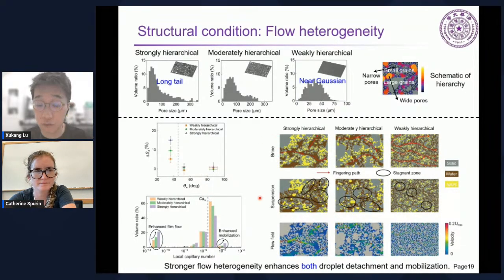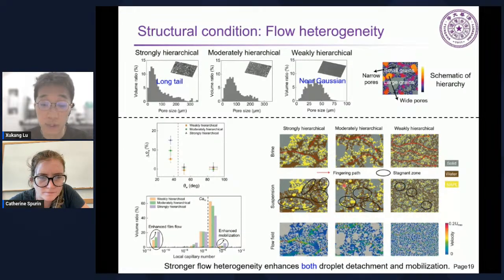And we try to analyze it from the qualitative comparison between the phase distribution and the flow field from simulations. So you can see clearly that the trapped droplets are basically released from the low velocity regions, the stagnant zones, where the local capillary number is very low and film flow is very strong, so that we have this film development and droplet detachment. And then we need to have these fingering paths so that the ganglia can be mobilized, because we have higher velocity there and corresponding higher capillary numbers there. So both statistics and qualitative observation agree with this interpretation that stronger flow heterogeneity will enhance both detachment and mobilization, leading to a better performance when we have nanoparticles.